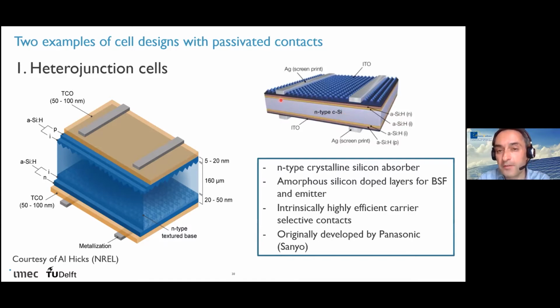So you actually have a sandwich of a crystalline silicon wafer between two layers of amorphous silicon at the front and rear. On top of the amorphous silicon, you typically have transparent conductive oxides for conductivity reasons, and then metal contacts at the front and rear. The metal is nowhere in direct contact with the silicon, because you always have the TCO and amorphous silicon layers in between. This concept has existed since the 1990s, originally developed by a company in Japan called Sanyo, which is now part of Panasonic.